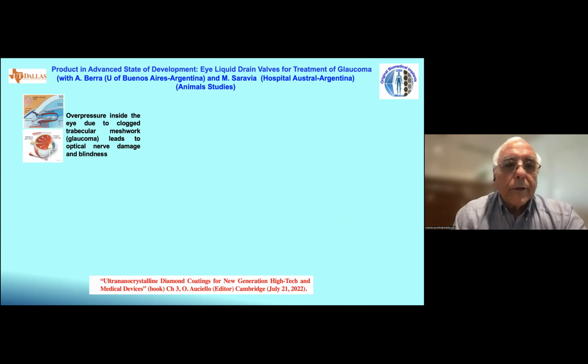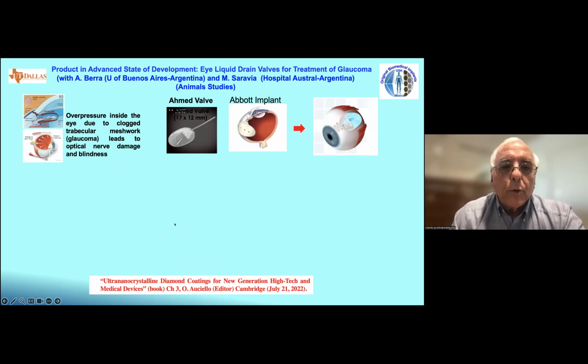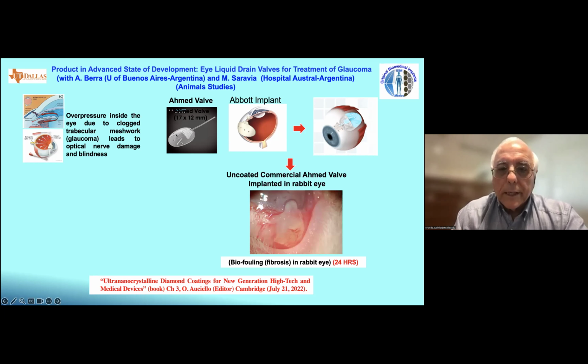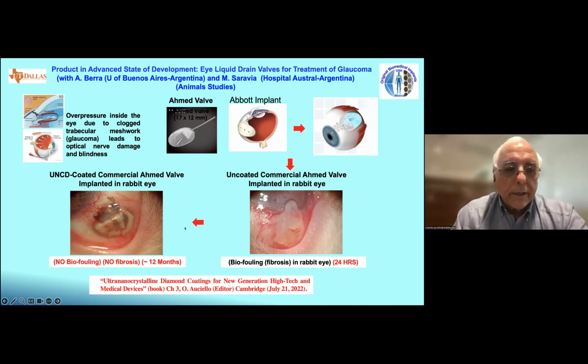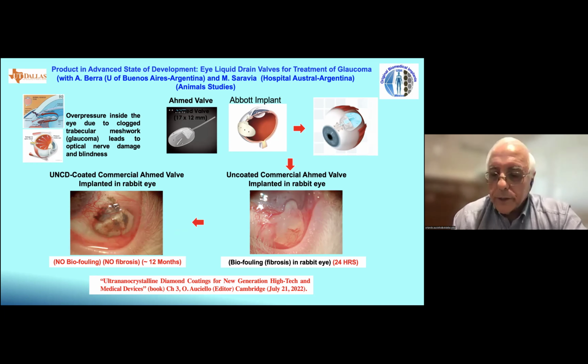So the other thing I am doing with my colleagues in Argentina is to develop a process, a UNCD-coated valve, like the Ahmed valve or the Baerveldt valve, that are used to treat glaucoma. Glaucoma is a condition produced by the clogging of the trabecular tubes in here that drain liquid from the eye continuously to keep the pressure of the eye normal. If that gets clogged, and if you don't drain the liquid, the person becomes blind. So the problem is that these valves are extremely hydrophilic, and in 24 hours you can get them coated with fibrosis. This is a UNCD-coated Ahmed valve, commercial valve, after 1 year, totally clear, because our UNCD can be made extremely super hydrophobic, as I'm going to show in the next slides.